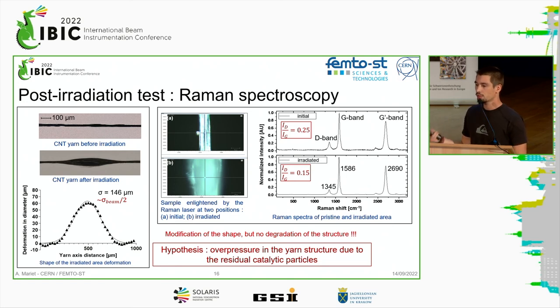But what did produce this deformation? We never observed that. An idea, but we are not sure at all, is that with the increase of the temperature, the iron just melted and traveled along the bundles, driven by the temperature gradient toward the cooler temperature. And there is an agglomeration of these different liquid or different states of iron creating bigger clusters and putting under pressure the different fibers, which broke and created this deformation. But that's something we need to investigate more deeply with other samples.